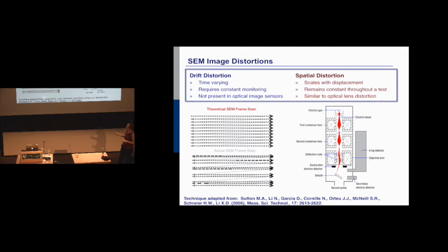The drift distortion is a little bit different. Once you set the spatial distortion, this is a lens thing, you set it at the beginning of your test, you're done. The drift distortion is trickier. This is time dependent. In a theoretical scan, you would dwell for the same time at every single point. You'd have a very well-behaved jump to the next line, and a very well-behaved jump to the next line. That's totally not what happens in an SEM. You can dwell for longer times, and then for really short times, and you can have a short jump and then a long jump, and this will change from image to image. So if you're trying to compare two images, and then the second time you do it your data points have shifted, you can't compare those.